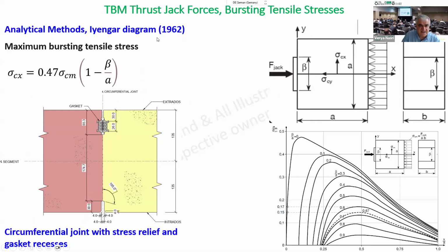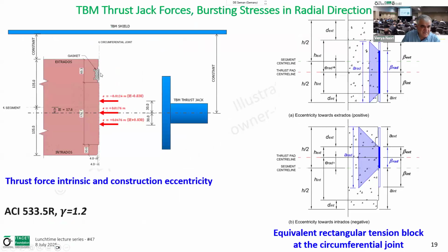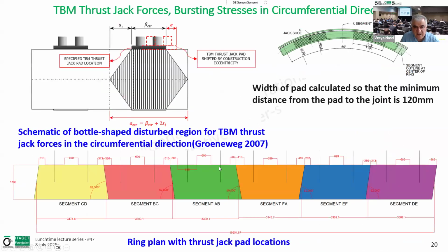So we use this Iyengar diagram, which is analytical. This formula here is drawn. Here you see the section in the radial direction. We have here intrinsic eccentricity because of the presence of the gasket. And we have to consider a construction eccentricity based on ACI, say 30 millimeter on both sides of this. Based on that, we do the calculation. We can have dispersion in both directions, in the circumferential direction also. You see here the configuration of the pads. So we have to design the size of this, but it should not be closer than 120 millimeter to the edge of the segment.